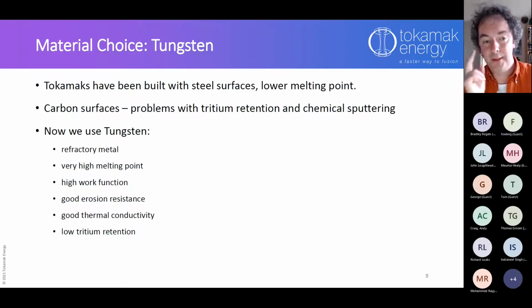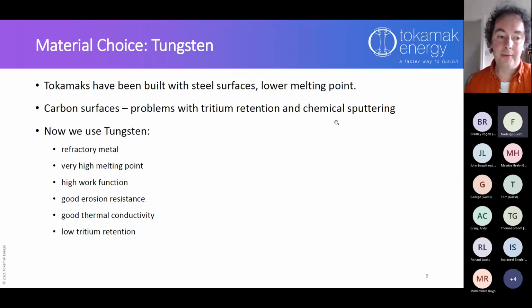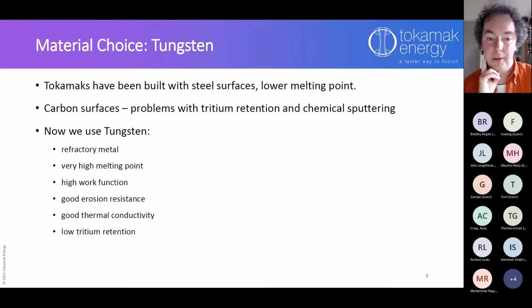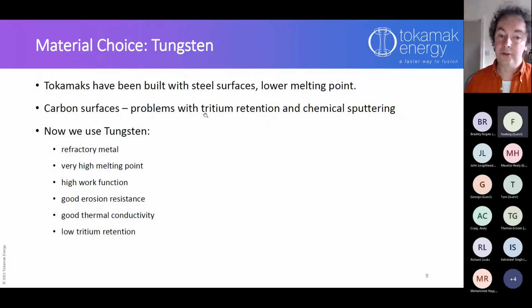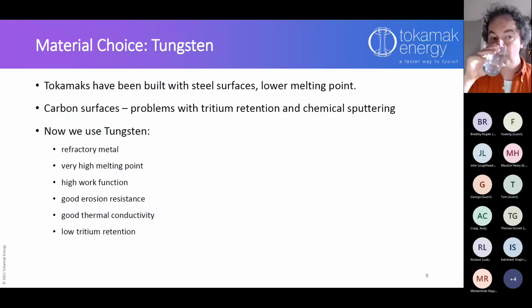What they then did was switch the material, and now their diverter is tungsten. So it's taken them 20 years to fit a tungsten diverter. They've done other things as well, and then redone those experiments with deuterium-tritium, and it's improved the fusion result, because you don't have these problems. So tritium, as I mentioned before, is radioactive. I think its half-life is about 12.3 years. So any tritium being retained in your surfaces is a big problem for things like maintenance and stuff.